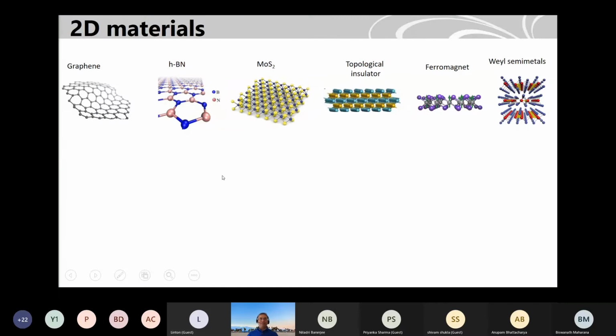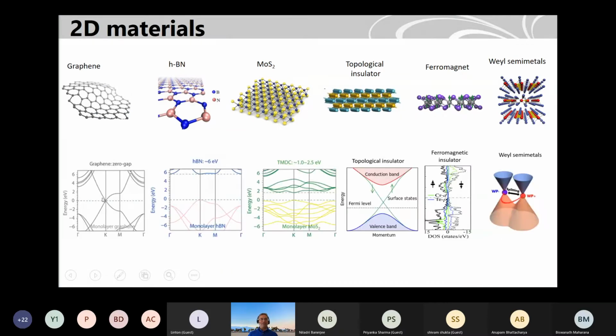So why are these different materials interesting? For example, graphene, as you know, has at low energy this linear band dispersion, giving rise to very high electron mobility and Dirac physics. At the same time, you can use boron nitride, which is an insulator, together with graphene for encapsulation, tunnel barriers, and gate insulators. Molybdenum disulfide is a good semiconductor with a high spin orbit coupling, and it has a band gap. They also have different valleys, so you can populate them independently with different kinds of spins.